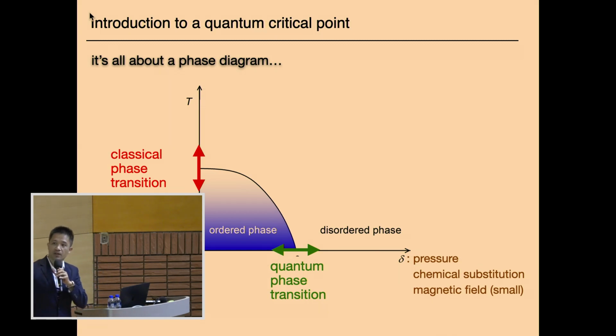If I vary the temperature along these red arrows and lead the system to go across this phase boundary, this is a so-called classical phase transition, which you are probably more familiar with. And if somehow I can use delta to suppress the ordering temperature down to T equals 0, and I start to play around across this phase transition, this is a so-called quantum phase transition, where the magnetic order is destroyed by quantum fluctuations. By the way, over here, the magnetic order is destroyed by thermal fluctuations.